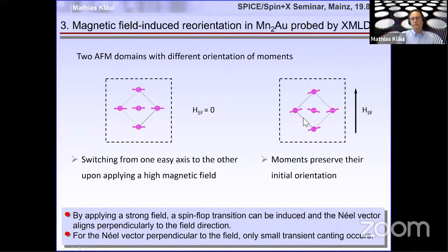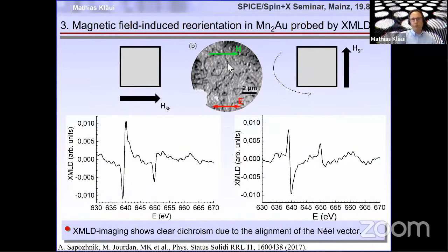And so what we did is we measured the X-ray magnetic linear dichroism spectra for a sample which we oriented by a strong field. So it's mostly monodomain, with the Néel vector pointing in one direction. And then we see that we have the spectrum where we get first a dip and then a peak. And then if we rotate the field by 90 degrees, we first get a peak and then a dip. So here we have actually rotated the Néel vector due to this applied field, but usually that takes a lot of field to do. Like in this case, maybe 60 Tesla. And that's difficult to implement in a CMOS device.